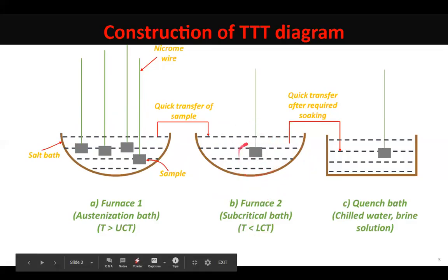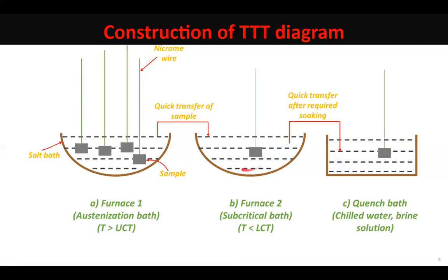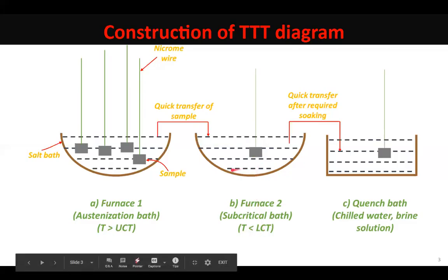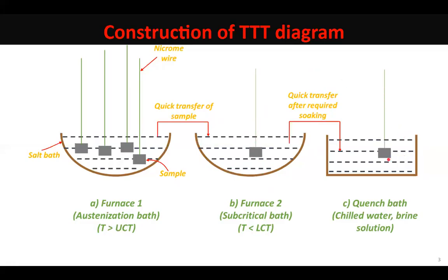Even if austenite transforms over here at a given transformation temperature and after spending some time at the transformation temperature, how do we get to know how much of austenite has transformed and into what product or product phases has it transformed? So what we do is, when we have brought the steel sample to this temperature and held it for a stipulated period of time, we immediately quench it. And when we immediately quench it, austenite transforms to a phase called martensite.